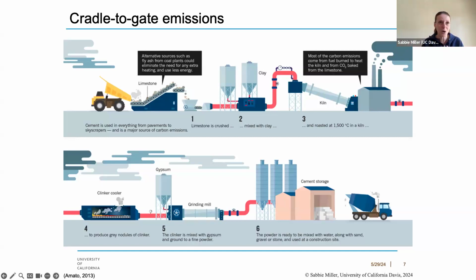And then you're going to form calcium silicates, which facilitate our calcium silicate hydrate systems, which actually allow for the formation of concrete that has nice rigidity, strength, durability characteristics, et cetera. That temperature that we need to form those calcium silicates is even higher than what we need for limestone decarbonation. So now we have a high temperature industrial process, which by and large, we're still using fossil fuels for.